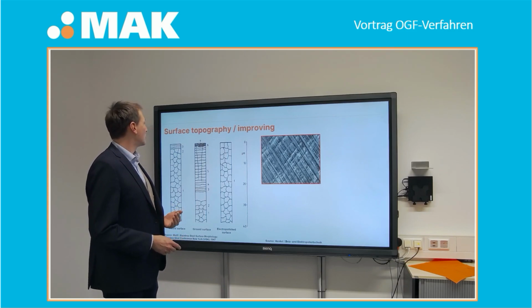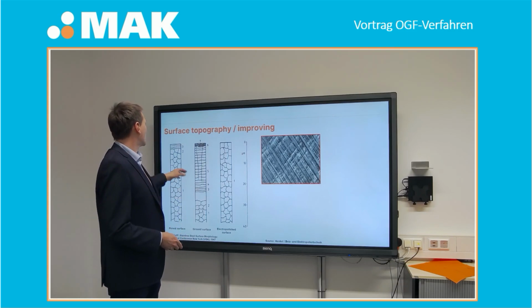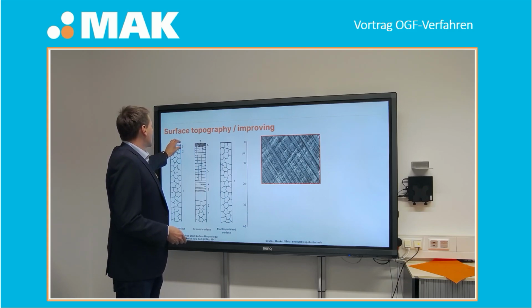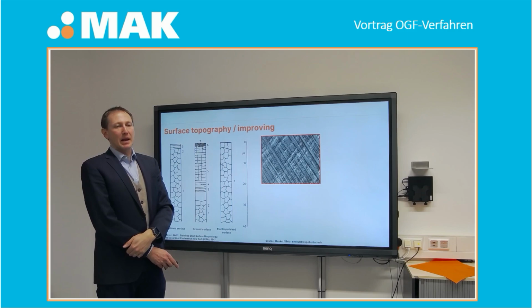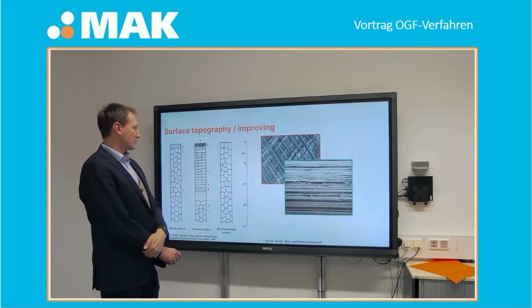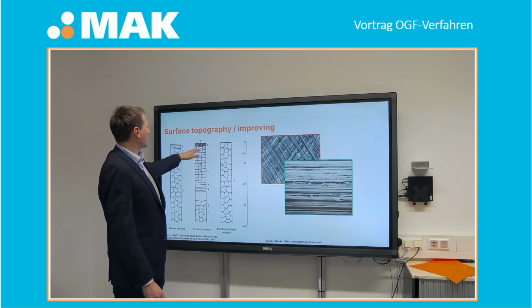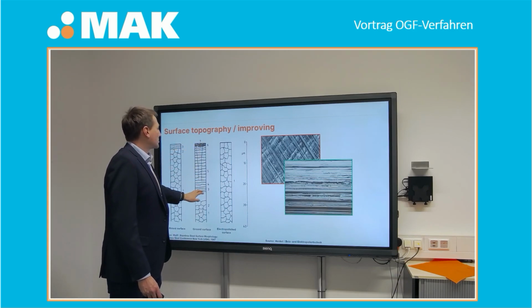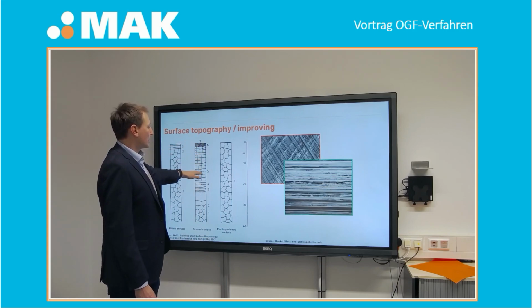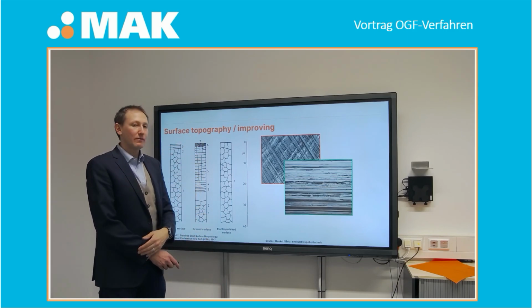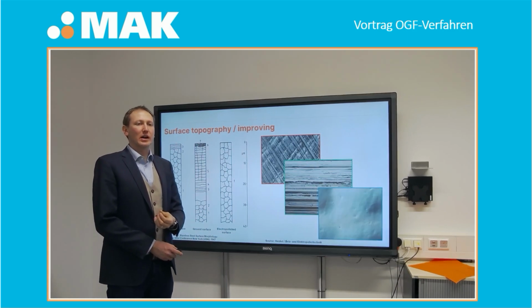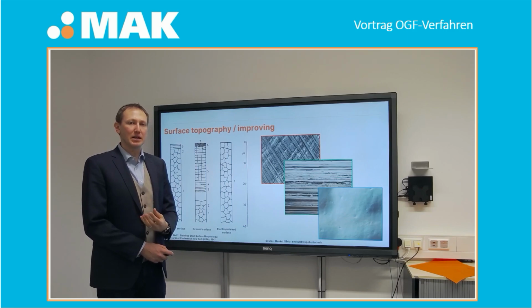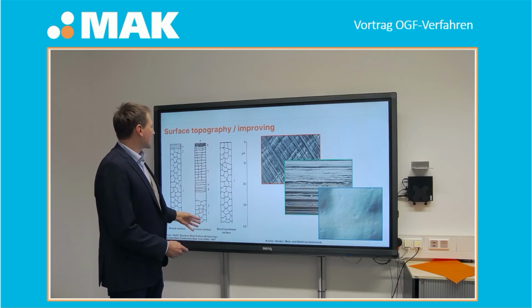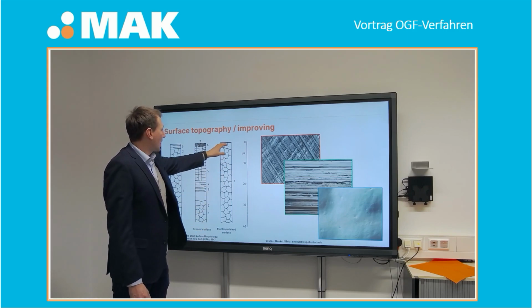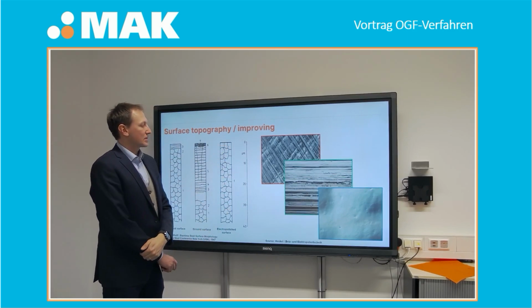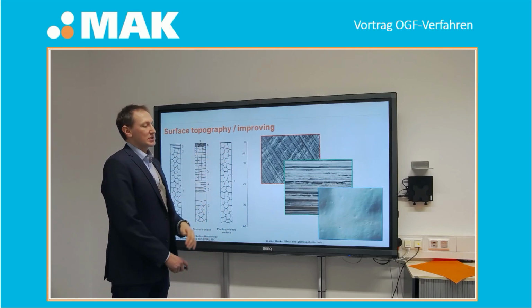and this so-called Beilby layer can be influenced by different ways of machining. If we do a smooth machining, like honing, on a honed structure, we have only a very thin Beilby layer at the top. If you do a harsh machining, a harsh grinding, we're influencing this Beilby layer down to several micrometers, maybe 20, 30, 40 micrometers into depth. And if we do electrochemical polishing afterwards, we are able to remove this Beilby layer, we are able to remove this deformed area, and so we have a very nice homogeneous metallic structure left without any deformation on the surface.